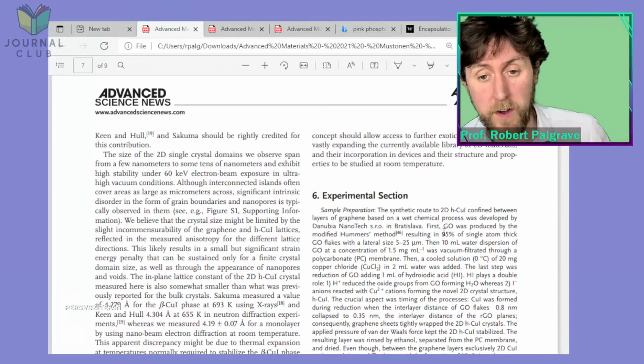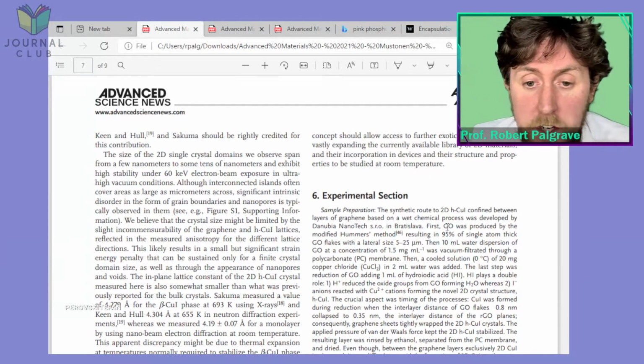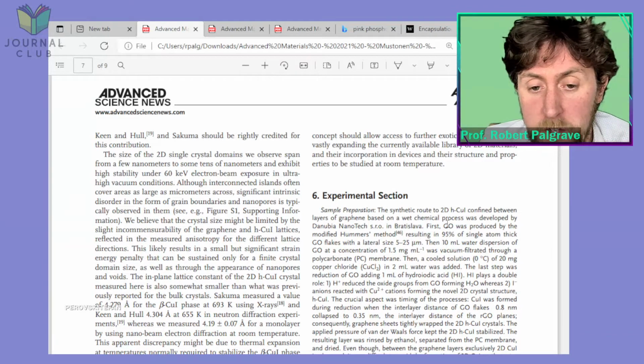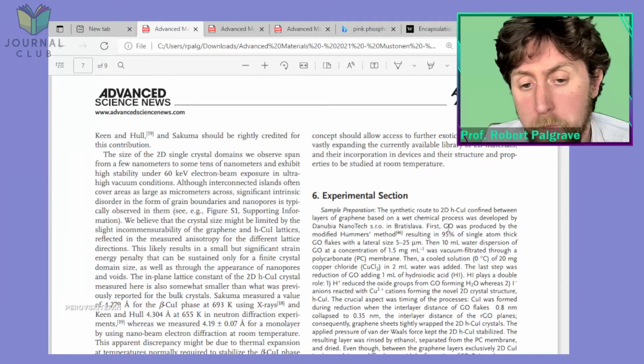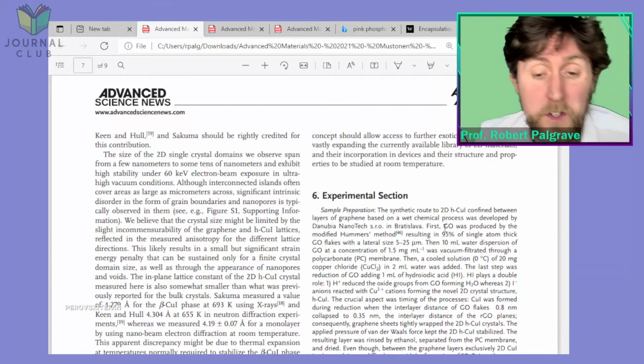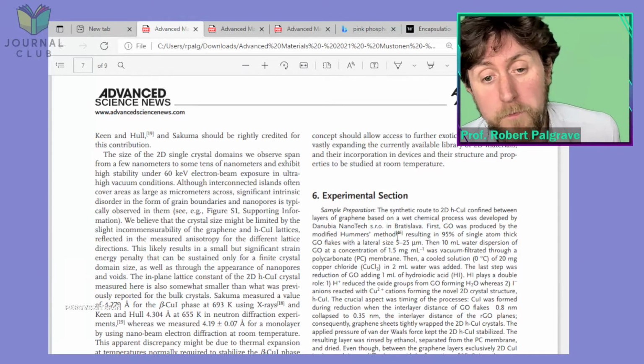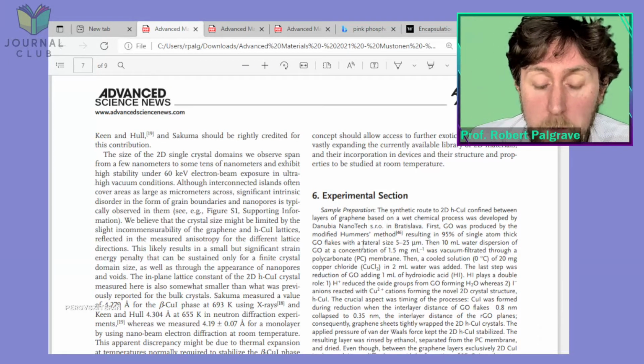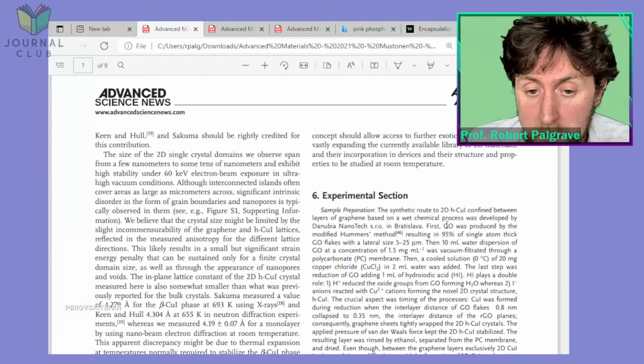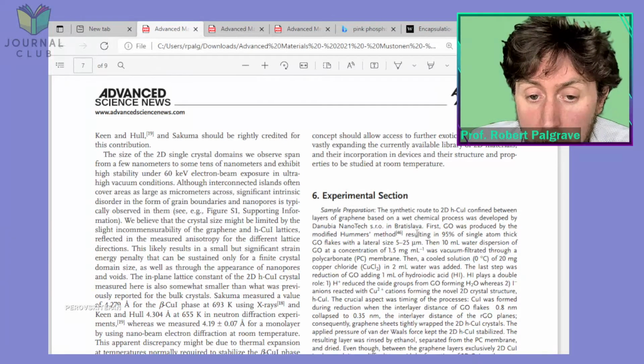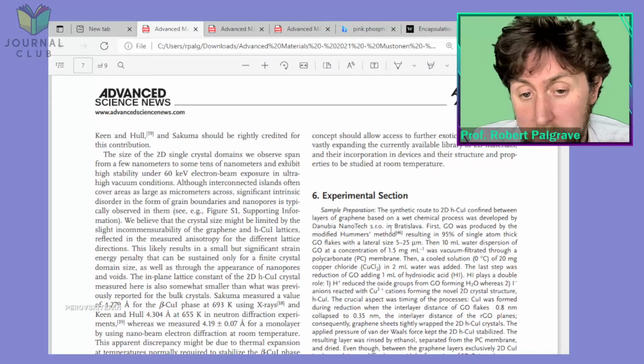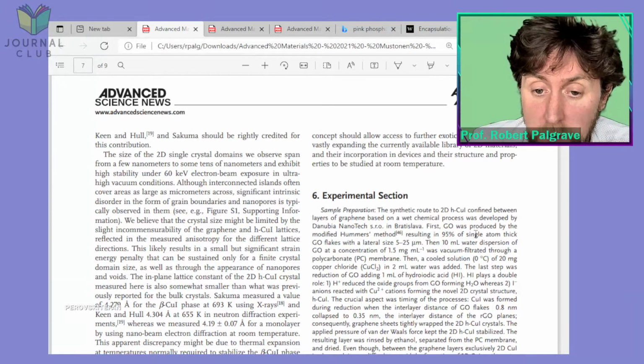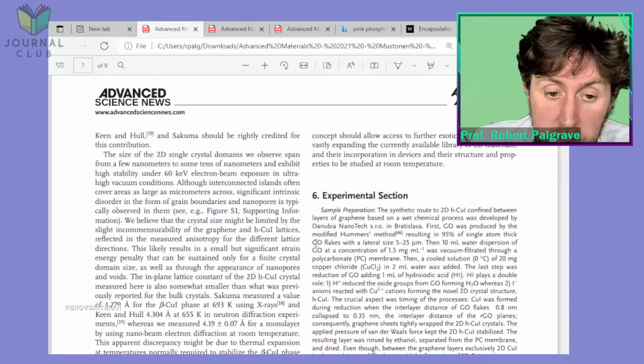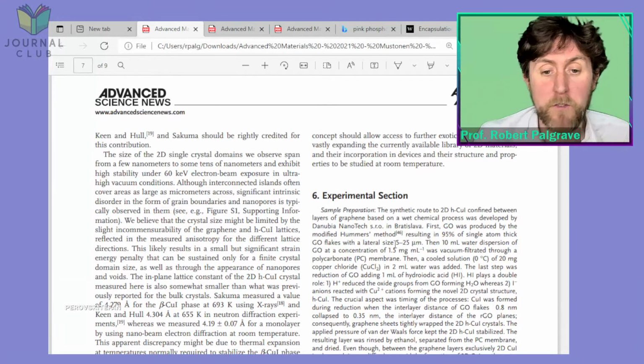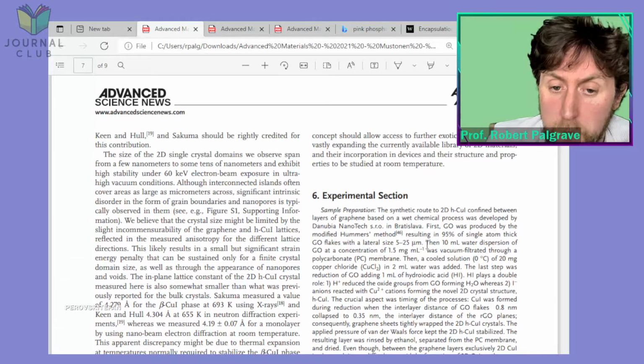It does still have some oxidation, some oxygen-containing groups on there, as opposed to being just carbon. Pure graphene would contain only carbon. But Hummers method is the go-to way to make graphene oxide, so much so that they don't even have to tell you how to do it, they just give the citation. The result is 95% single-atom GO flakes, graphene oxide flakes, with a lateral size of 5 to 25 micrometers.